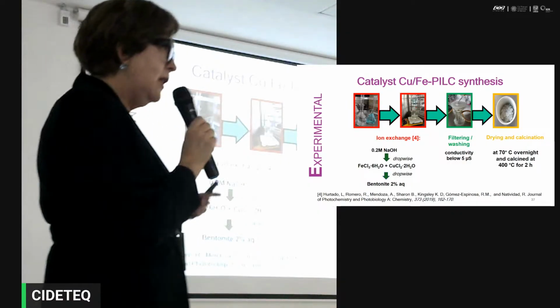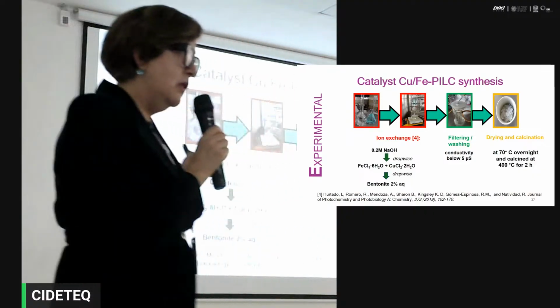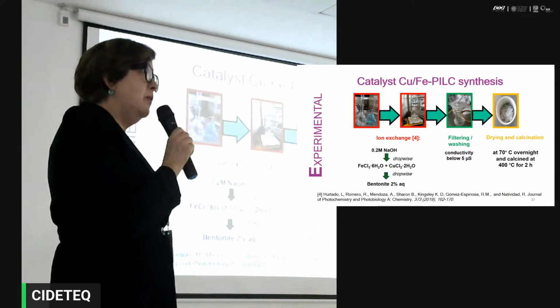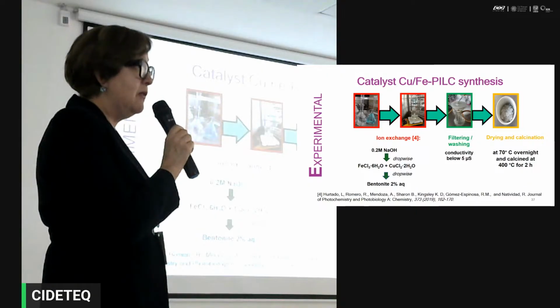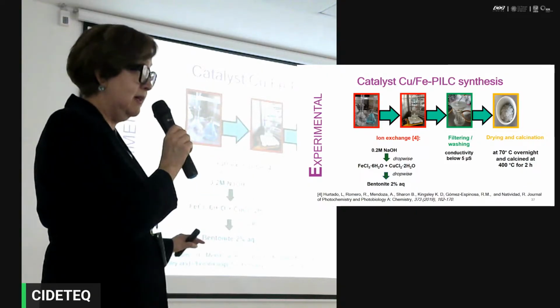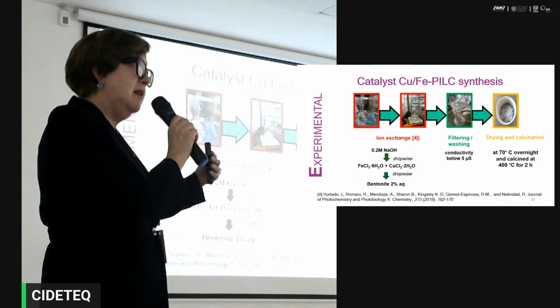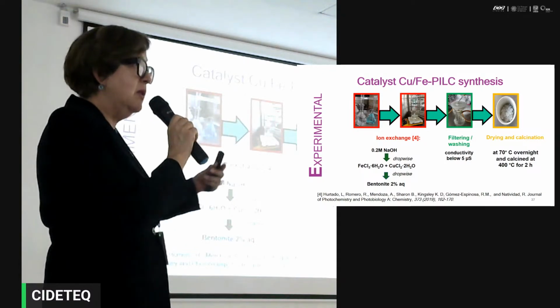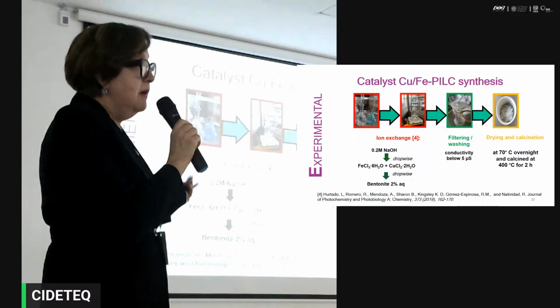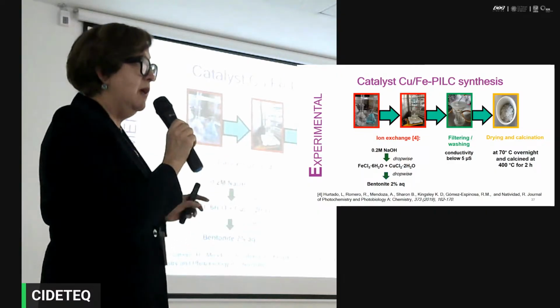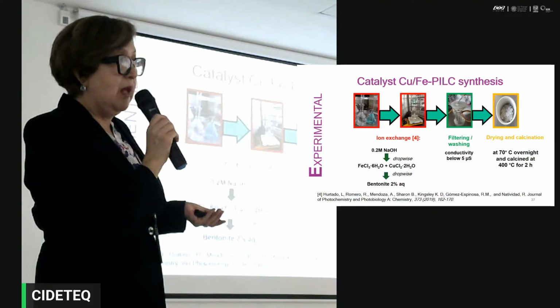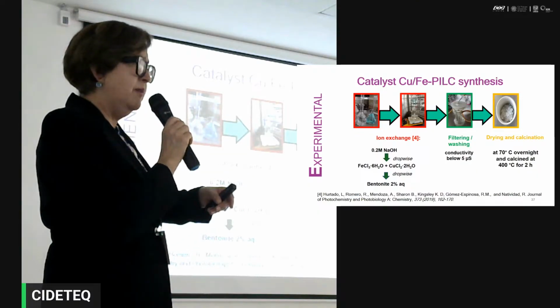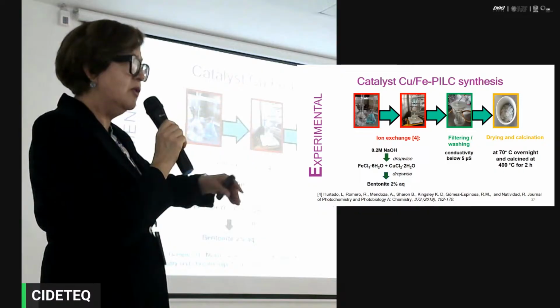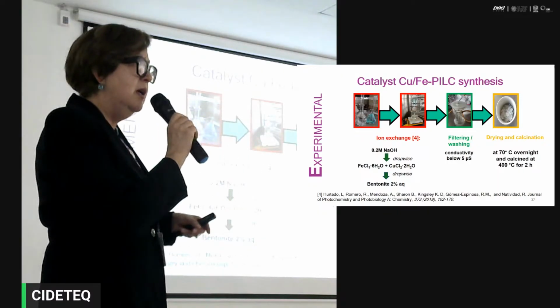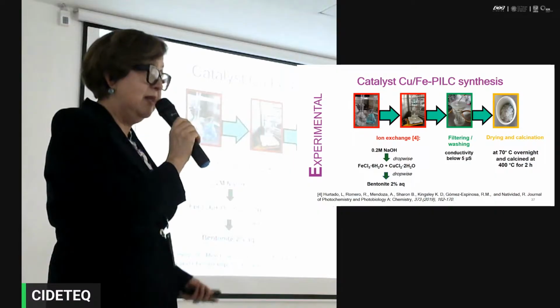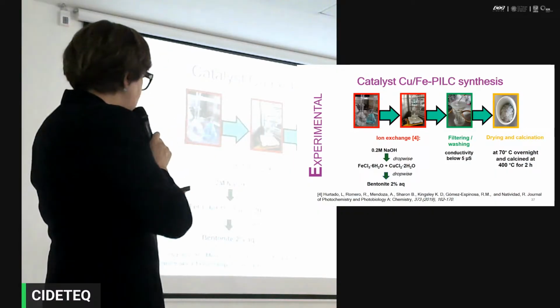Okay, well, the way that we observed that it was a catalyst was because we conducted experiments only with bentonite, and we observed the reaction. The reaction is already conducted only by bentonite. The formic acid concentration is increased when we added the pillars, the metal pillars. But then, well, there is that contribution of the bentonite. And the second question was how the source or the composition of the bentonite could affect. We believe that it is because of the Lewis acidity that is changing.